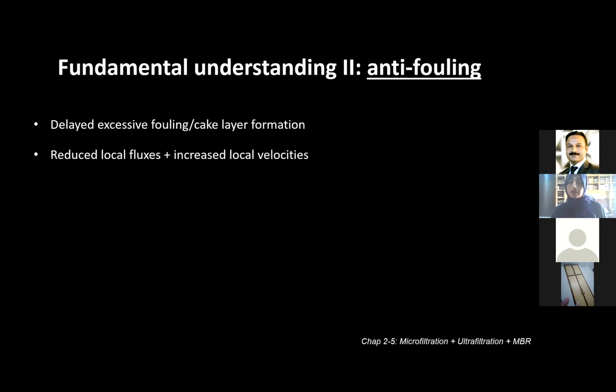So both of these factors are contributing in their own perspectives. Perpendicular orientation was better in improving the hydrodynamics, but parallel orientation had a dominant effect of this increased surface area.